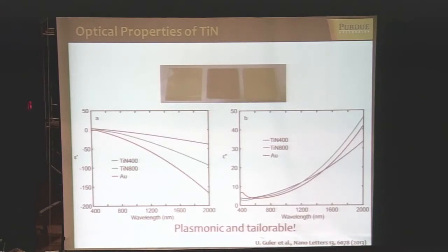You could really tune it, as opposed to gold—it could be as negative as gold, or less negative, simply by changing the conditions under which you make the material. For example, these two titanium nitride samples were made at two different temperatures, 400 Celsius and 800 Celsius, and they have very different real parts of the electric permittivity. In terms of the imaginary part, it's still a lossy material, but what we obtain is a magnitude very similar to that of gold.